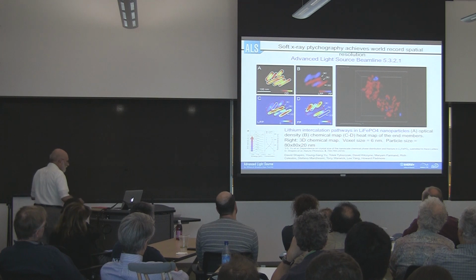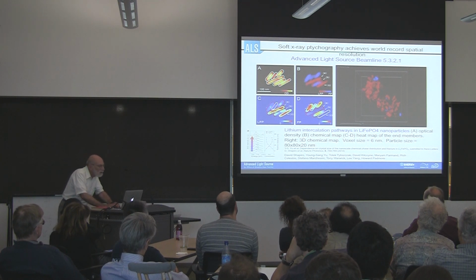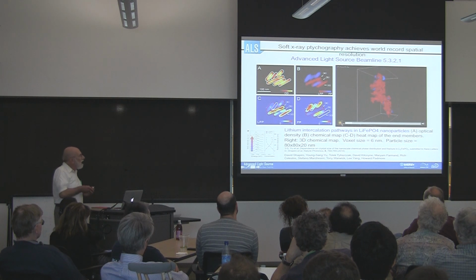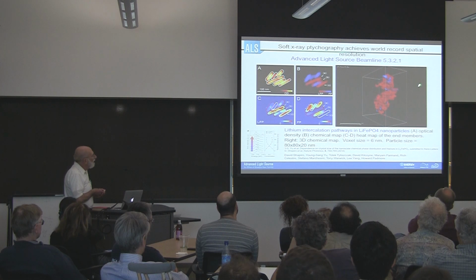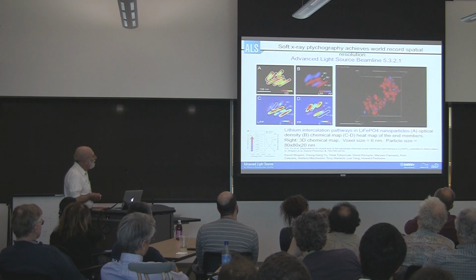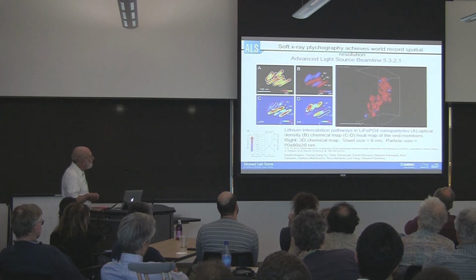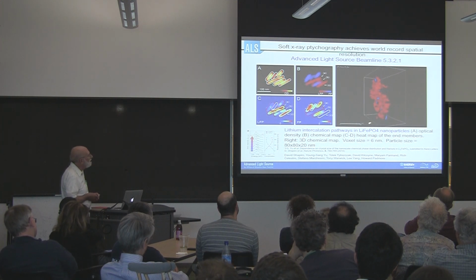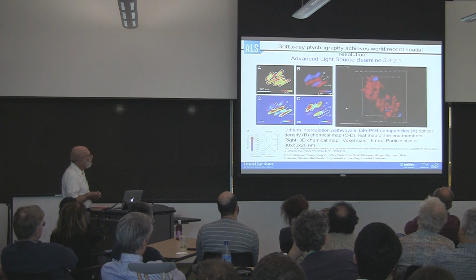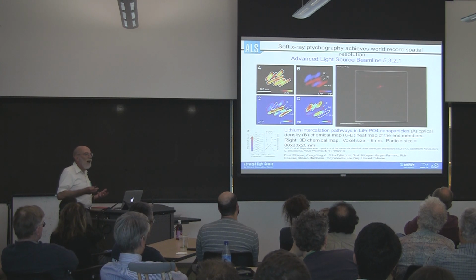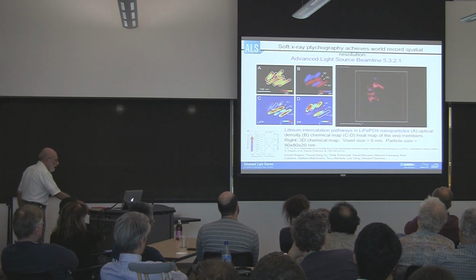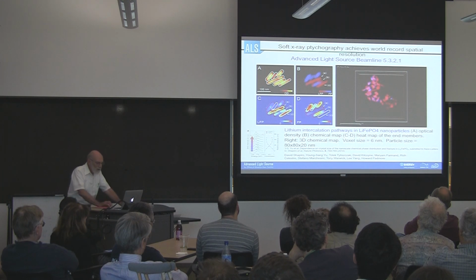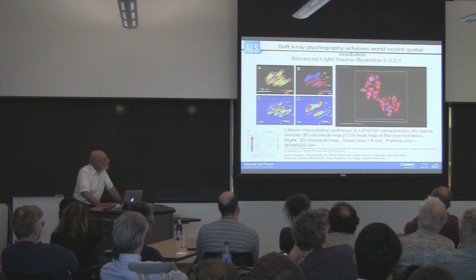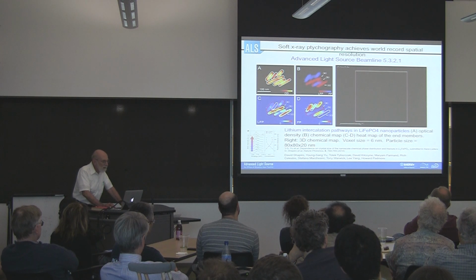And you can do that even in 3 dimensions. This is a little granule of this battery material. The entire size is 80 by 80 by 20 nanometers. So the resolution is just a few nanometers across, and you have it with chemical speciation. You can use this technique to find at very high resolution in 3 dimensions what chemical component is where.